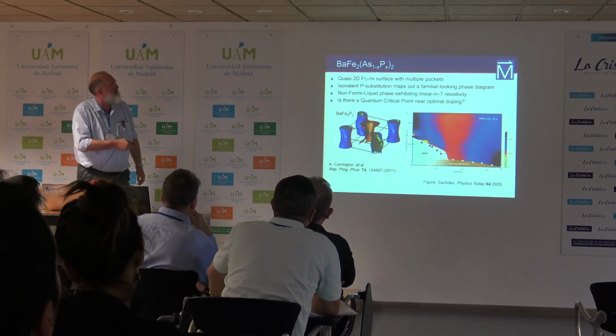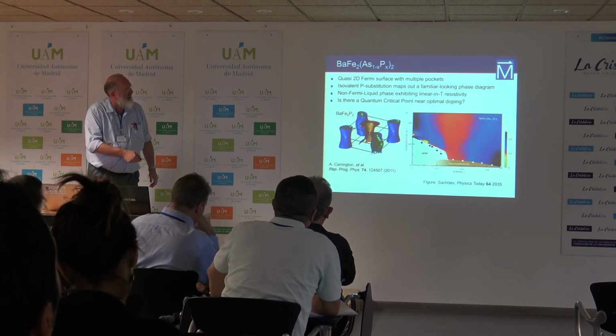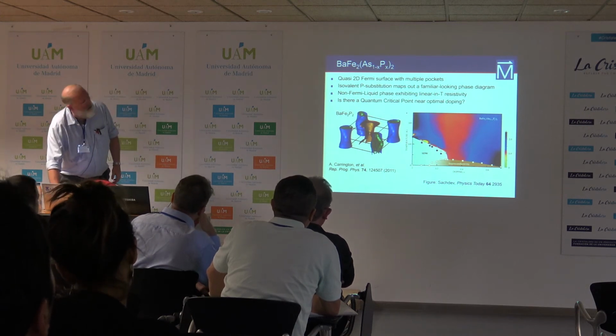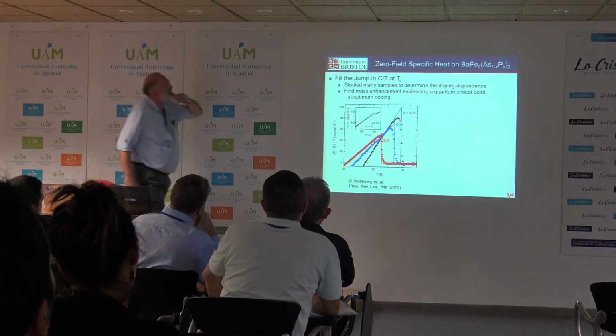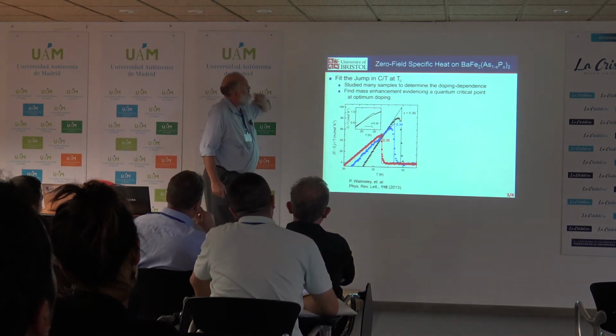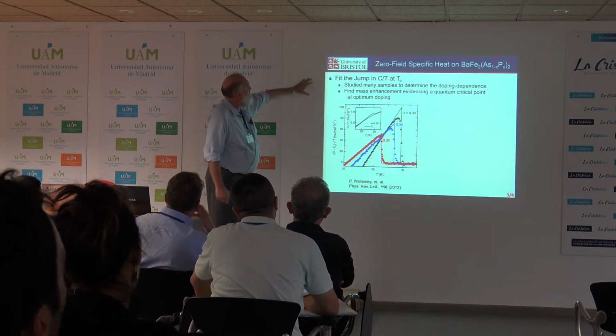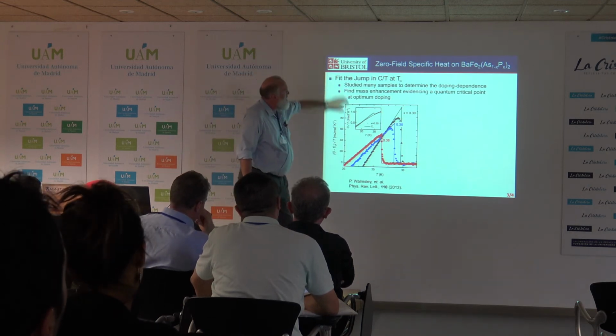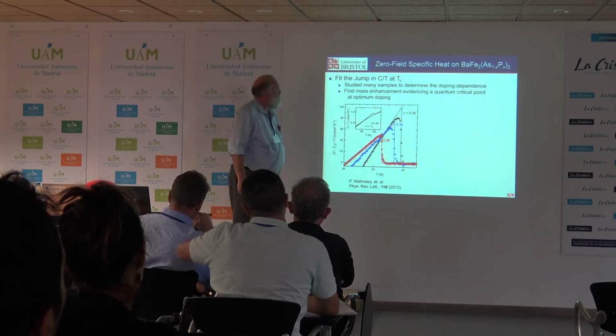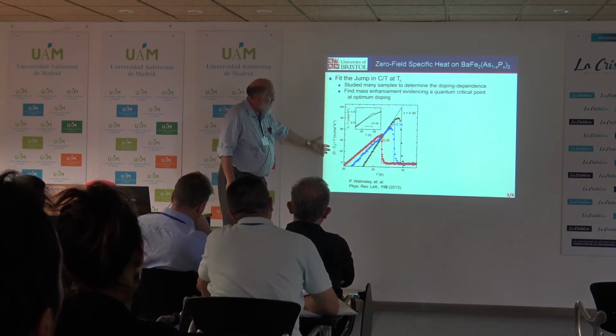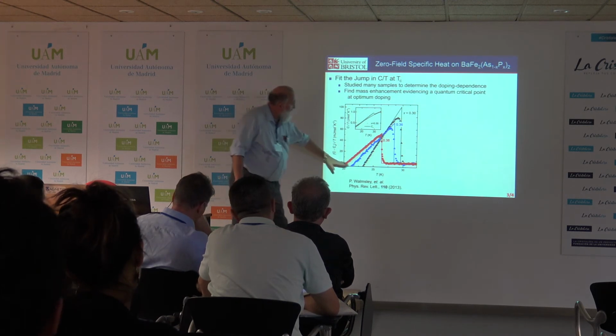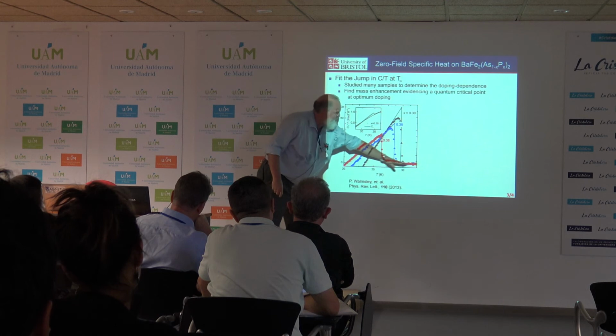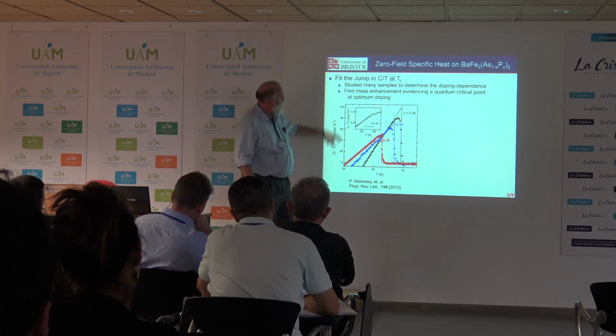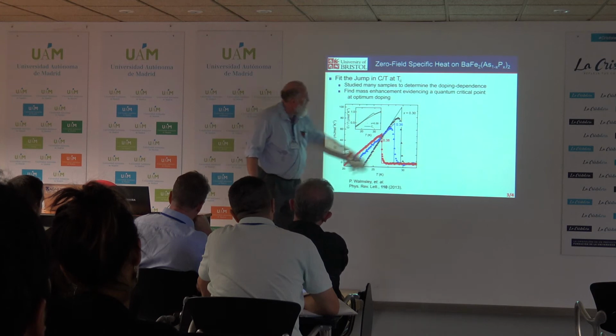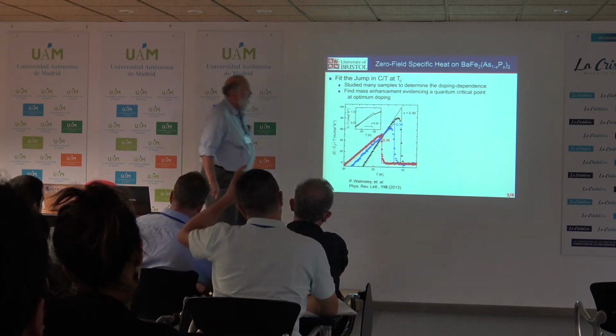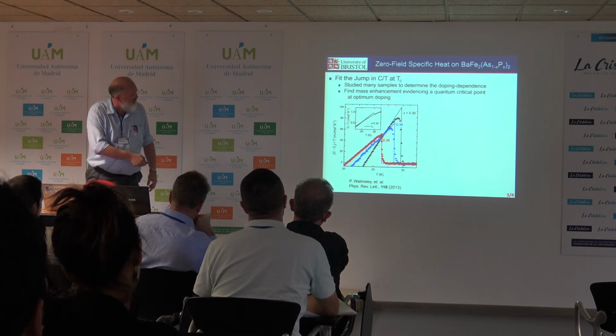So this has the non-Fermi liquid exhibiting linear in T resistivity, and the question is, is there a quantum critical point near optimum doping? Well, the first evidence of mass enhancement comes from work by Tony Carrington. He's fitting the jump at C over T at TC. So these are zero field measurements, C over T, after subtracting out the normal state. So this would be the normal state up above TC, and it's just 0 on this plot, so that he can then give us in millijoules per mole Kelvin squared the size of this jump at TC. This is the reference for that work.